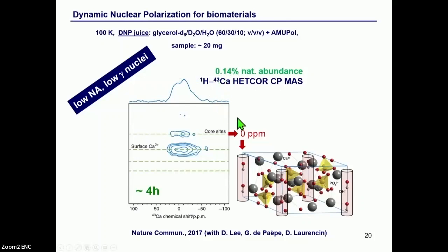But by using the DNP and by selecting the correct DNP juice, you all know that it's possible to enhance considerably the signal-to-noise ratio. In this case, we were able to record in 4 hours the first two-dimensional experiment. It's a HETCOR type, correlating a calcium dimension to a proton dimension with a distinction here between sites, and it was then possible to assign the correlation peaks by going back to the structure of hydroxyapatite.